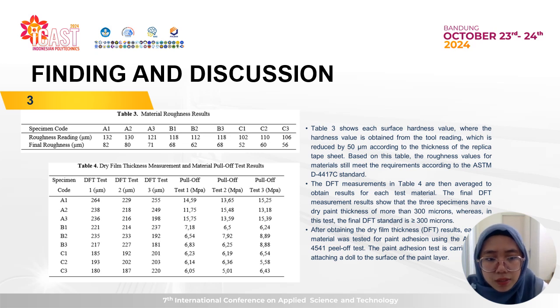After the visual inspection, we got the material roughness result. Table 3 shows each surface roughness value, where the roughness value is obtained from the tool reading, which is reduced by 50 micrometers according to the thickness of the replica tape sheet. Based on this table, the roughness value of the material still meets the requirement according to the ASTM D4417 standard. And you can look at Table 3 for each specimen code A, B, and C.